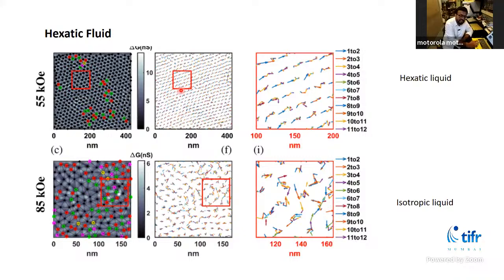So we took very thin molybdenum germanium films that we have grown using the pulsed laser deposition setup that we have shown. And here you can see that at 55 kilo-oersted magnetic field, vortices are there, but they are not solid. As you take images, for example from 1 to 12, from each image you can see there is a little movement of vortices in this zoomed part. And in your regular liquid, what happens? Your atoms are free to move in any direction whatsoever. That's why it's isotropic. The liquid is isotropic. But this hexatic phase, one characteristic of this is that it is not isotropic. This will only flow in the directions of your underlying lattice.